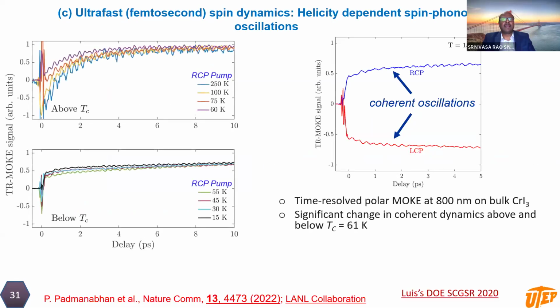So we went ahead and did a bunch of experiments at Los Alamos National Lab. These are pump-probe measurements. We took this crystal and measured the time-resolved MOKE signal above the Curie temperature as well as below the Curie temperature.